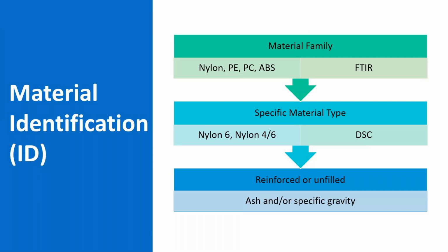And so we would start with figuring out the material family, FTIR. So again, it would tell us if it's a nylon or polyethylene, ABS, whatever family it would belong to. Then we could do DSC to determine within that family what material it is. And then the last one is just an add-on, would be if it's reinforced or not. So we would do the ash test if we suspect that it's reinforced, or if we don't suspect that it's reinforced, we can do a specific gravity to check that real fast.